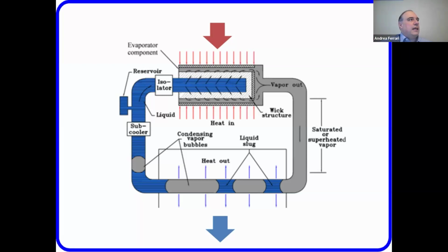This system does not have moving parts, so the only part that moves is the fluid, and it also doesn't have a switch, which is a problem, because if you don't have a switch and it doesn't start, you have no way of intervening. So it has to be very well set when it comes to self-starting.